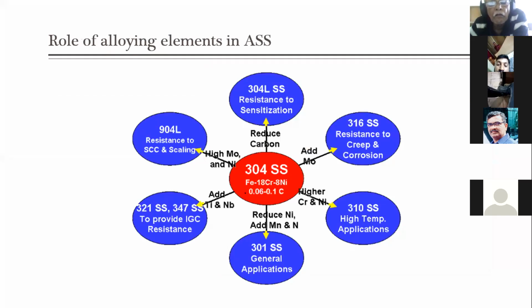And coming to the role of alloying elements in austenitic stainless steel, the commonly found grade is 304. If you reduce the carbon content in 304 SS, then you get 304L SS. L is nothing but lowered carbon content when compared to 304 stainless steel. Here you will have reduced carbon content, which increases the resistance to sensitization. And if you increase the molybdenum content of the 304 composition, then you can have very good resistance to creep and corrosion.